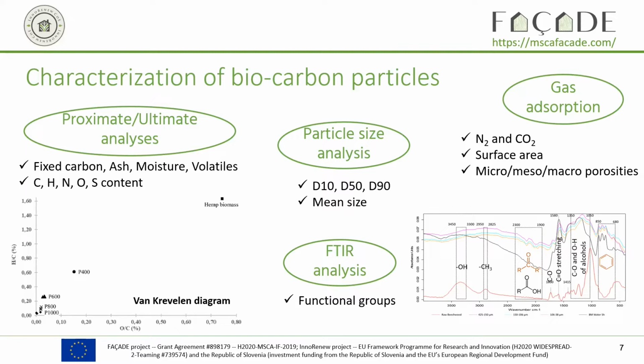And generally, when we carbonize the biomass, we start from medium carbon content, and we go toward higher carbon content, and we decrease the hydrogen and oxygen content. So on the bottom left, you can see a typical Van Krevelen diagram, where we see that the higher the temperature, the lower the H/C and O/C ratio. And this will be important for some properties of the biocarbon.